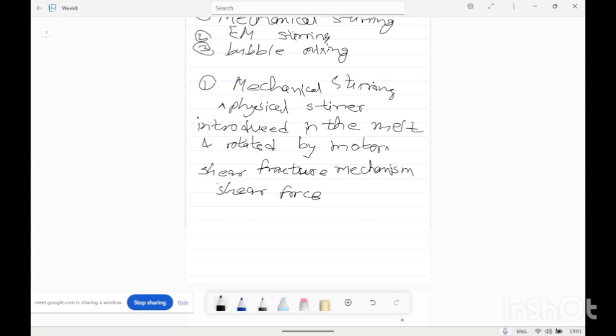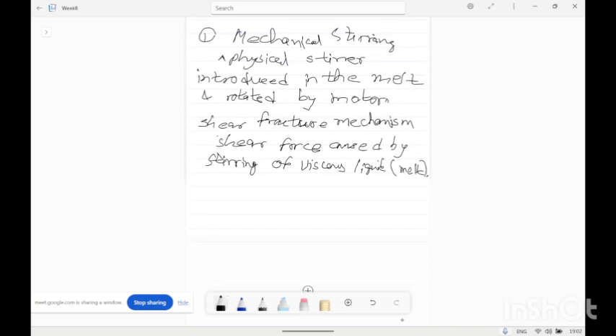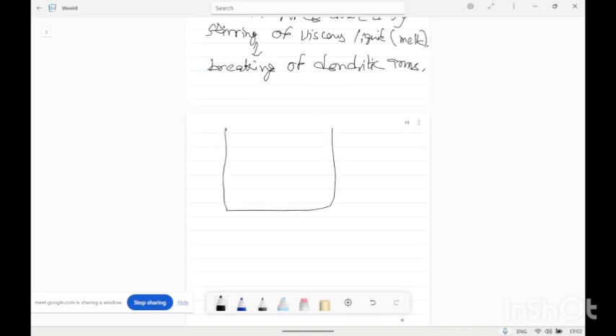Shear force caused by stirring of viscous liquid, means melt. So the shear force generated in this process leads to the fragmentation and breaking of the dendrite arm. Dendritic arms means, as we see in the solidification process, at the mold surface the small grains generate and will grow as dendrites into the melt.